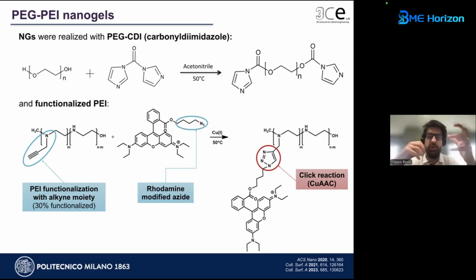On the opposite, in order to reduce that, we said, okay, if we use something more hydrophilic, these objects can be less selective for microglia. So this is why we decided to move on, because the first point is to reduce the uptake by microglia, then increase the uptake in astrocytes. But the first is reducing microglia, because if all of the nanoparticles enter within microglia, we obtain another selective system for microglia, not for the other cells. So we decided to use nanogels, which are more hydrophilic.